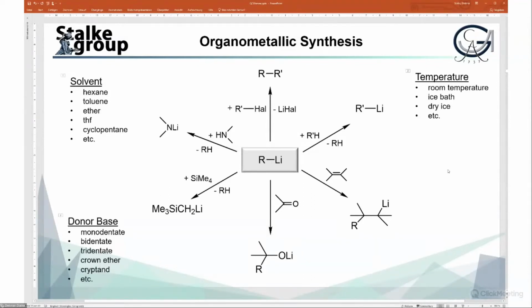Then the donor base is important to deaggregate the lithium organics. Whether you use a monodentate, bidentate, or tridentate donor base matters a lot. Or you could create solvent-separated ion pairs where you break the lithium-carbon bond and isolate the lithium in the donor base, like a cryptand. So that changes reactivity.